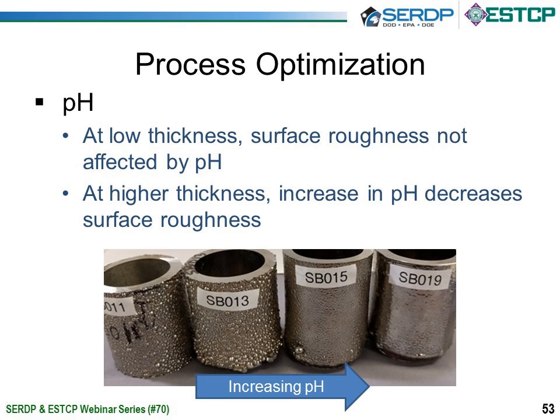However, as the thickness deposit increased, a lot of nodule formation was observed. And this was actually found to be reduced just simply by increasing the pH of the solution. The picture in slide 53 shows deposits of similar thickness. Those on the left were produced at a lower pH, and those on the right at higher pH. There are clear differences. Obviously those on the right are quite a bit smoother than those on the left. There are still some nodules there, so there's still some minor improvements needed. But overall, it did show that increasing the pH to a specific level was important for producing thick deposits.